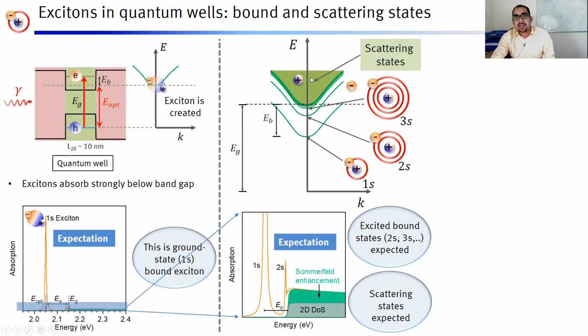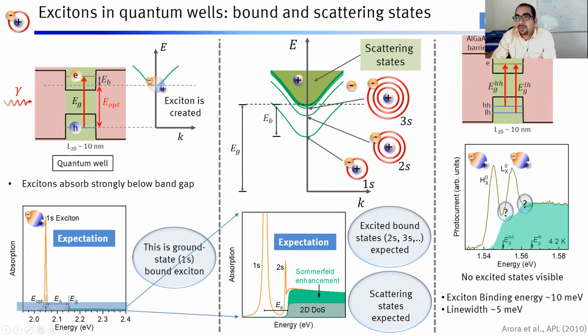However, the scattering states also have some Coulomb interaction in them, so they enhance the absorption spectrum, and this is called the Sommerfeld enhancement. So without them, you will expect this, but with Sommerfeld enhancement, you will expect this. So it should fall a bit, in fact, while going to higher energies. So this is what we expect. These are expectations. Now let's look at the experiment.